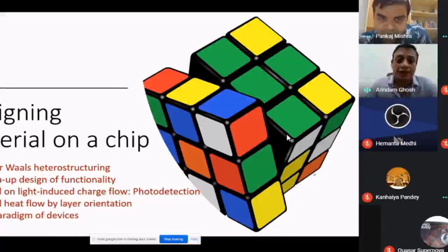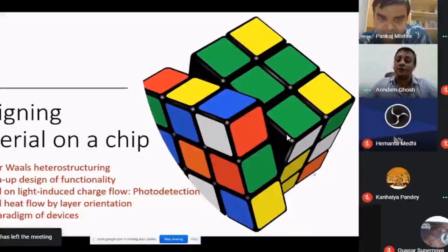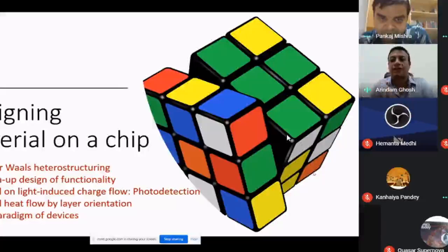So we have found that now, and we have done some Raman spectroscopy on that. And we have found out that the electron-phonon coupling between two layers changes from a large value at 0 and 60 to a small value in the 30 region, which has been computed as well. I'm really sorry I could not show that, but I hope I gave you an idea of how to determine the angle.